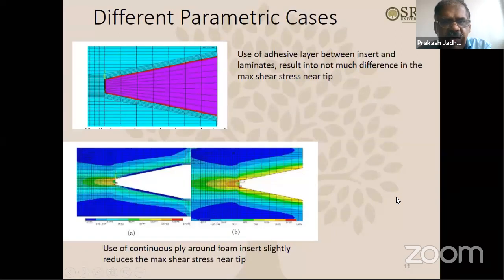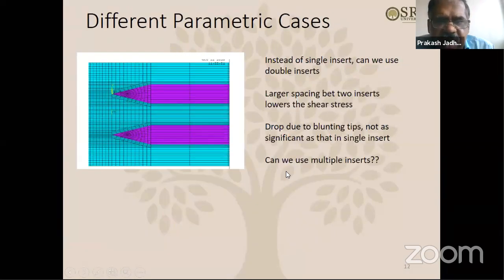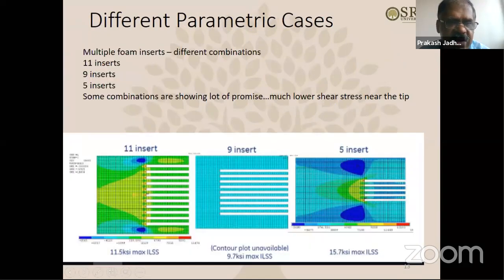Then going forward, we thought about why only one embedded foam insert? Why can't we have multiple foam inserts, maybe two or three around the cross section? As you can see, one example is shown here: instead of one single big foam insert, can we have multiple foam inserts like this? We tried two foam inserts, three foam inserts like that. Larger spacing between the two inserts lowers the shear stress. The drop due to blunting tips is not as significant as that in a single insert. Then going forward, instead of this double insert, we thought, can we use multiple embedded polymeric inserts? This is the example shown here.